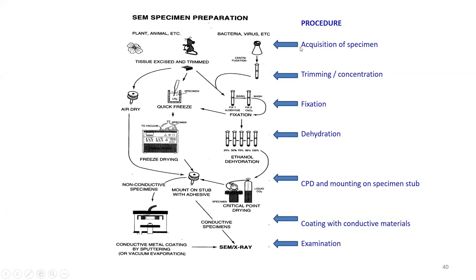Okay, so typically this is the flow of how things work for specimen preparation for SEM. If you're working with a powder sample, like dry formulations or APIs like we do sometimes, you simply take the powder, do a sputter coating, that is coating with a conductive metal, and go ahead and observe under the microscope. But for biological SEM, if you're working with cells, tissues and things like that, you have to follow an elaborate method, which is again not as demanding as TEM, because here you only want to preserve the surface features of your specimen.